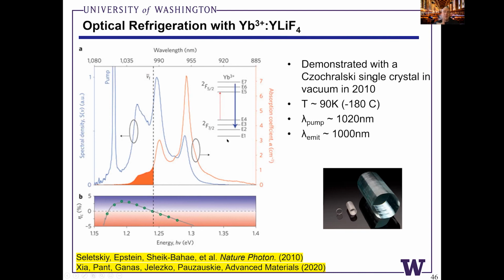So if this is efficient enough, if you can get near unit, 100% quantum efficiencies, you can pump a material with a red laser, say, on the red line, the low energy side of its absorption band, and then it can emit a blue shifted photon that carries away both the pump energy you pumped it with and whatever thermal excitation, whether that's a collision or phonon from the material. And it cools, in general, a bulk material.